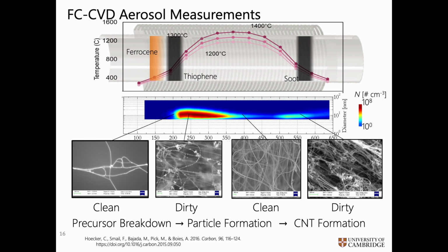And what happens is your reactants break down initially, in particular your ferrocene and thiophene, that's your iron and your sulfur source. And when they break down, what's shown here in the heat map, on the y-axis, is the diameter of the aerosol particle. So we're extracting these particles and making size distribution measurements along the axial location of the reactor here. So these are plotted to scale here. And what you see is initially when the ferrocene, and particularly the thiophene, the sulfur, breaks down, you get a burst of nucleation and those catalysts grow.